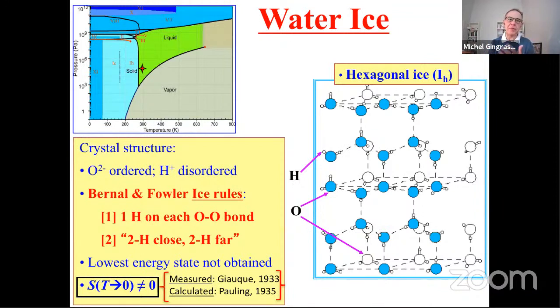What are the rules that the protons should obey in order to understand ice as being a hydrogen bonded crystal of water molecules? These are well known in chemistry, or in the science of water hydrogen bonding. They are called the Bernal and Fowler ice rules, after the two chemists that enunciated those rules. So what are the rules? The first rule is that between each oxygen-oxygen bond, there can only be one proton. Because if you have two protons on the same oxygen-oxygen bond, you have too much electrostatic repulsion between the protons, and that will not lead to a ground state or a low energy configuration.